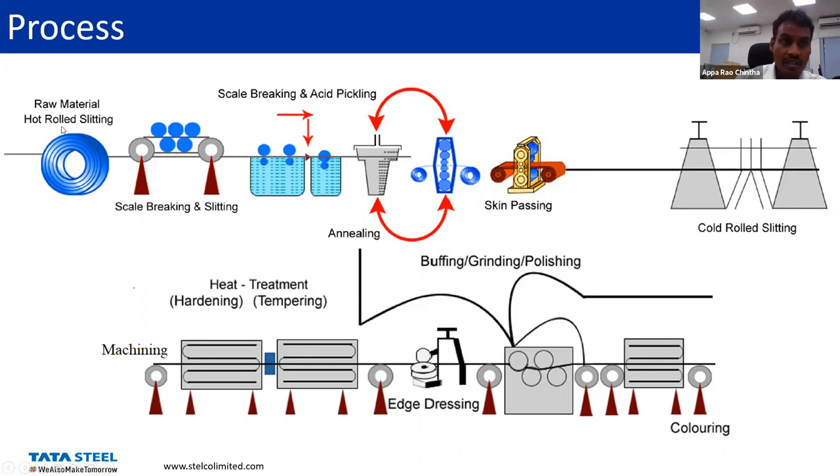The input material in most cases is ferrite and pearlite — hopefully full pearlite, or pearlite plus cementite, as in the case of high-carbon flat steels. The final one is the hardening: quenched and tempered martensite. These components go for end applications where wear resistance and hardness are required. The intermediate process is only to increase machinability. After machining, all the components go for a hardening treatment, and hence this process itself is an intermediate process.